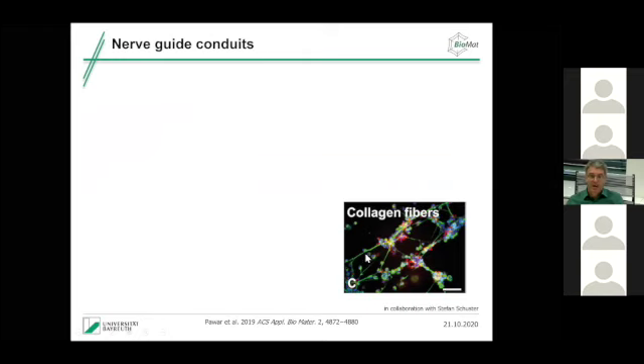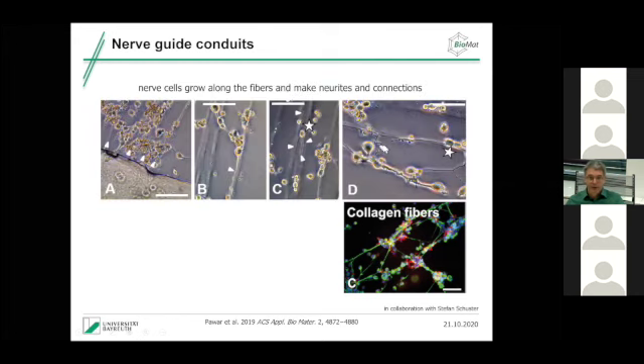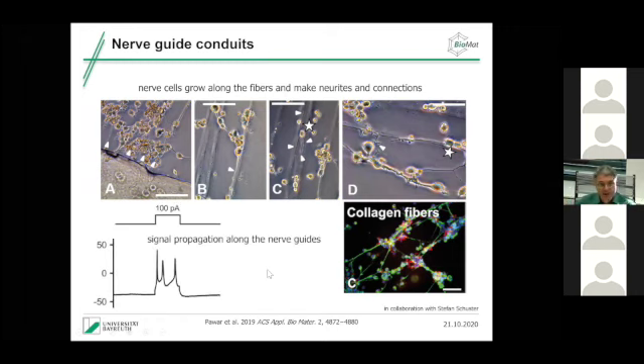We see that the neurons really make neuronal networks. They interconnect, and you see here the connection points between the neuronal cells along the fibers. And we can even measure in vitro the signal propagation through these conduits immediately 2 days after cultivation. 2 days versus 6 months. And I think this is a huge improvement.